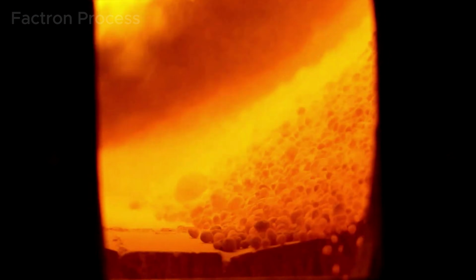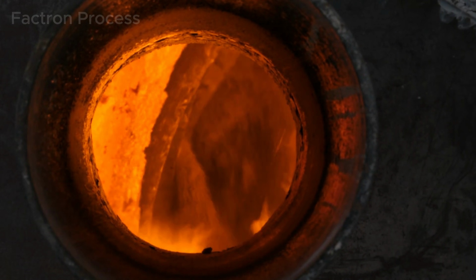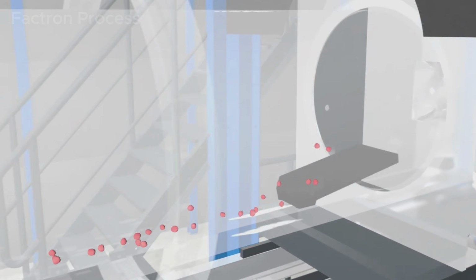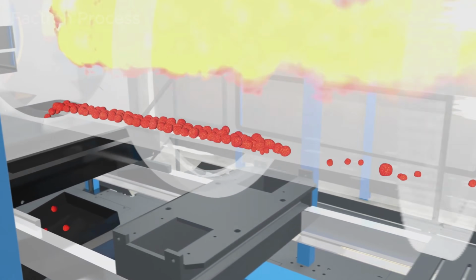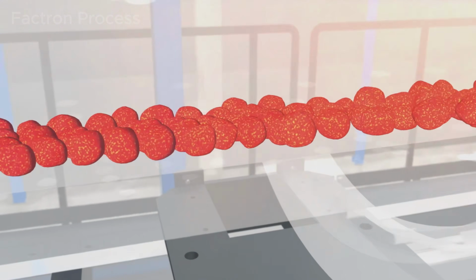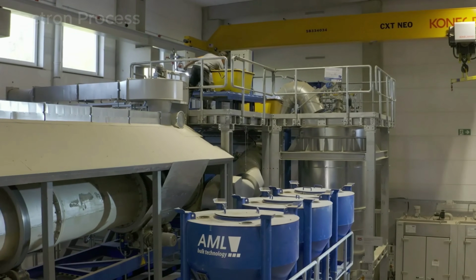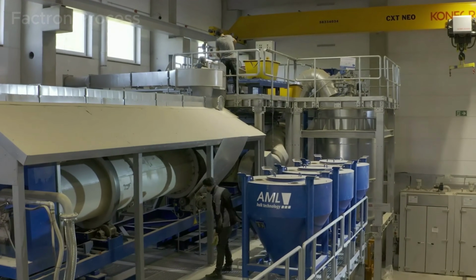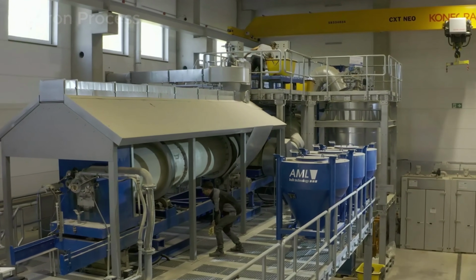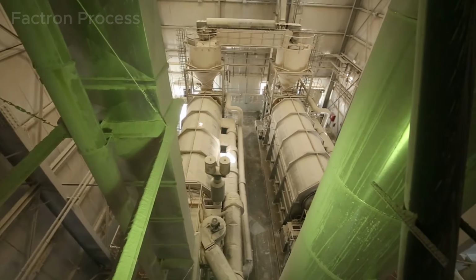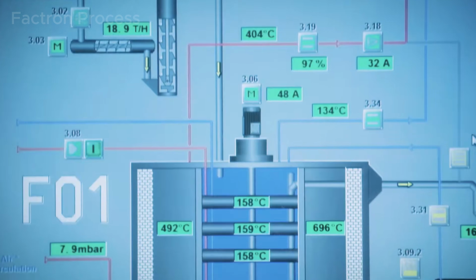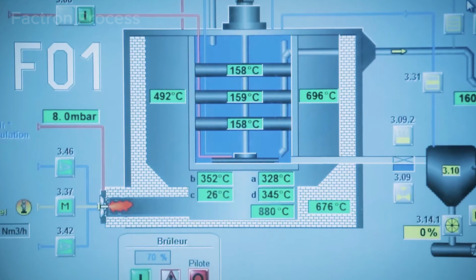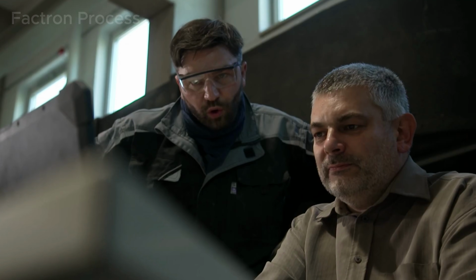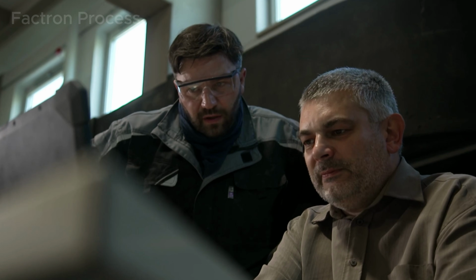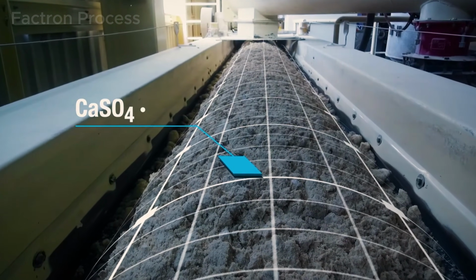Over several minutes, about 75% of the crystallized water is removed from the natural gypsum. As a result, calcium sulfate dihydrate gradually turns into calcium sulfate hemihydrate, commonly known as stucco. This is the moment when gypsum's real value is created. Before this stage, it is simply a white mineral rock. After leaving the kiln, it becomes a material capable of hardening again when mixed with water. Nearly every modern drywall panel begins with this chemical reaction inside these enormous rotating kilns.